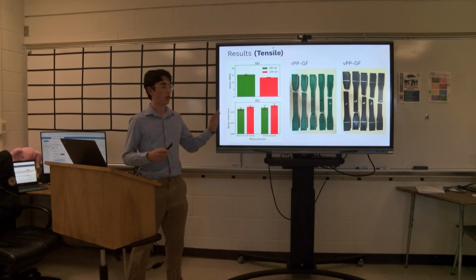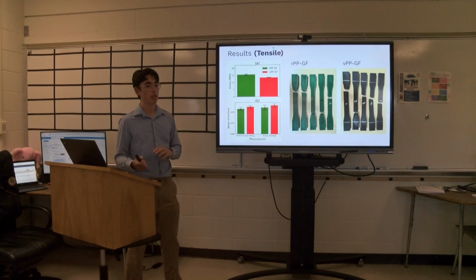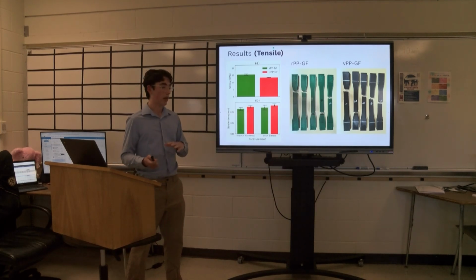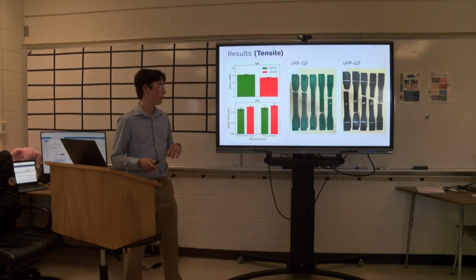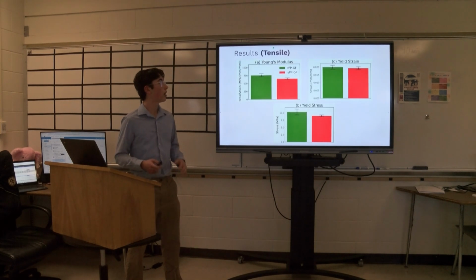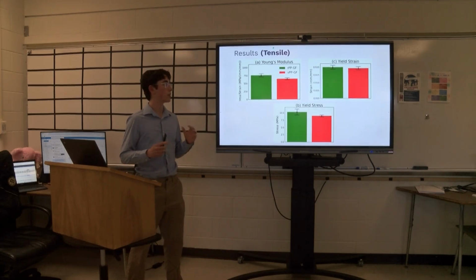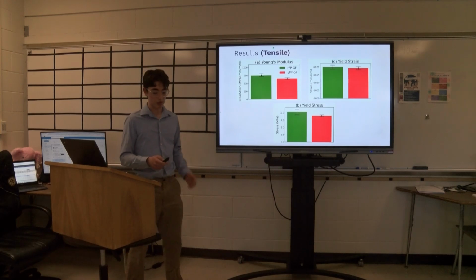We can see that there's little plastic deformation in the specimens at the break area, which means that there's brittle fracture, and the fact that the recycled material also failed at a lower elongation means that it is also more brittle, which is something we saw earlier. Now, the other results, the Young's modulus, yield stress, and yield strain, further affirm this. The recycled material has a higher Young's modulus and a higher yield stress. The difference in yield strain was pretty much negligible, so I didn't really compare those properties between the materials.